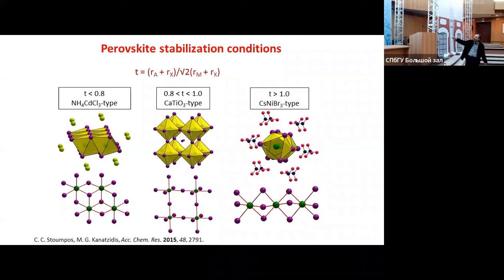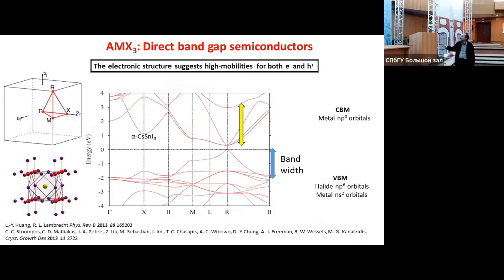It has been found that the perovskite structure needs to be in this region. If the A site cation becomes too small, the perovskite cavity collapses in, and you form a different type of one-dimensional structure, much less interesting. And if the cations are too large, the cavity opens up, and you again get a non-interesting structure, which is only one-dimensional, where the lattice expands in one dimension in a different way this time.